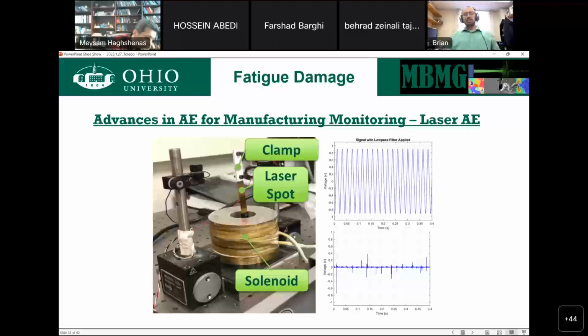And what that means is we have the ability to acquire what you see on the top right and the bottom right. The top right is the vibration I'm applying through the solenoid in order to cause this material to bend. I can monitor that throughout the entire test, and I can monitor the acoustic emission, which is the bottom right, the higher frequency content, throughout the entire test. And I'm doing this with a single sensor. One laser can do both. I just need a filter to whichever range I'm looking for.